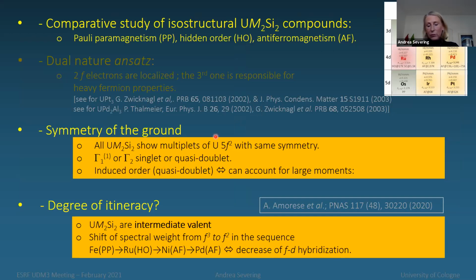And with this, I'm basically at the end of my talk. I think I have shown you that we are on top of the ground state symmetry. We're finding a gamma 1 singlet, or rather a quasi-doublet, that can accommodate the large ordered moments that all four compounds here, the iron, the ruthenium, the nickel, and the palladium, have in common. All compounds are intermediate valent, and we find a decrease of fd hybridization in this sequence.